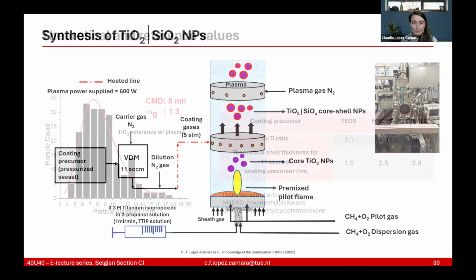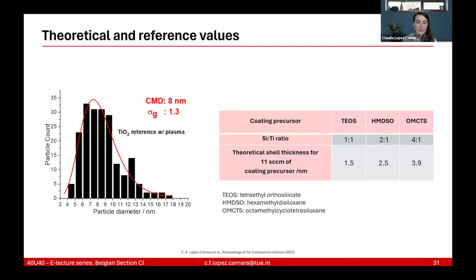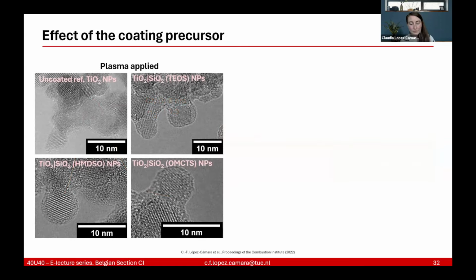So with that, we thought, well, we depart from titanium dioxide nanoparticles as a reference with the plasma included, but without shell, because we want to study the shell. So those nanoparticles are about 8 nanometers. And based on that, we decided to choose TEOS, HMDSO, and OMCTS as 3 different coating precursors, because each of them has a different silicon to titanium ratio. So 1:1, 2:1, and 4:1, respectively. And therefore, the theoretical shell thickness was supposed to also differ and be higher as you move towards OMCTS, as higher ratios.